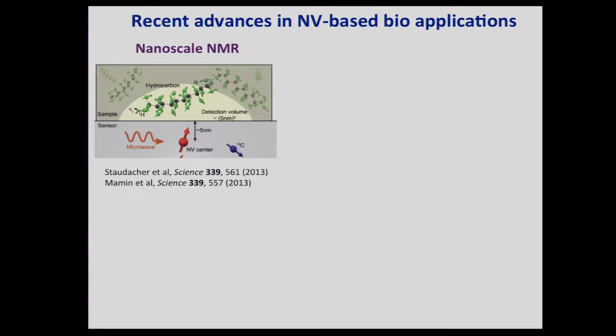I'll show you some experiments from our lab later that give you a little more detail on this type of experiment. But the point is that this is doing magnetic resonance imaging, or NMR, on a volume much smaller than anything commercially available in standard magnetic resonance imaging today, where the state of the art gives you tens of microns of spatial resolution. The ultimate goal here is to get to the single nuclear spin limit. Partially the goals in my lab, as well as those of our collaborator Dan Rugar at IBM, are to image the structure of proteins by doing nuclear magnetic resonance on the individual nuclei. So this is a really nice step in that direction.